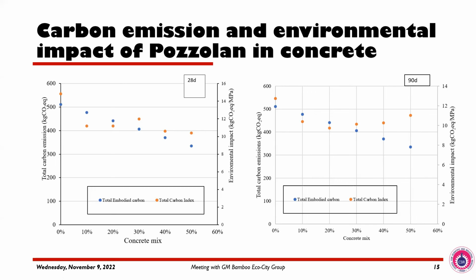So that one should be driving us when we are doing construction, because there is a vast difference between curing at 28 days and curing at 90 days. So if your project is not time bound or whatever, you can actually slow down and then let the thing cure very well and then achieve a proper high strength. However, there have been projects that I have done that they require higher early age strength. So I dope it with accelerator to achieve higher strength at early ages, but it also comes with a cost.